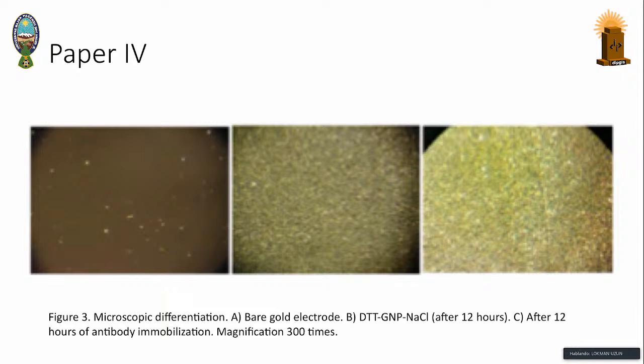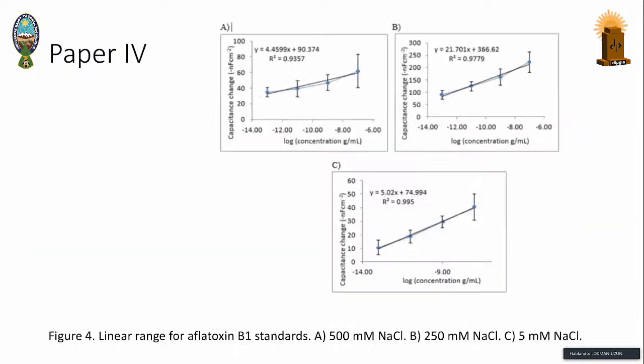In this study, you see in here, Alvaro showed us a very narrow size distribution achieved by these gold nanoparticles, and a proper concentration range. They achieved an applicable response in a linear working range. A very important parameter that excited me when I read: sodium chloride is used as a counter ion to trigger the aggregation between gold nanoparticles. It has a big effect on the performance of the electrode as well.